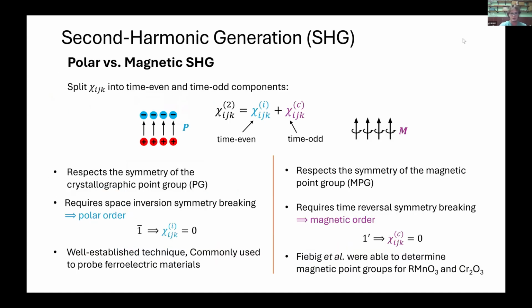Now, the one slightly different thing with this project is we're also looking for this time-odd component to the second harmonic generation. So this is a bit separate from what people typically do in characterizing ferroelectrics. This polar component is time even. It ignores any magnetic symmetry, the magnetic point group. But once you break your time reversal symmetry, you can have this time-odd component that reverses sign under time reversal, and it will have different selection rules. So this you can use to identify your spin structures in an antiferromagnet, for example. And Manfred Fiebig, in his work, essentially pioneered this technique, looking at rare earth manganites and chromium oxide, stuff like that.